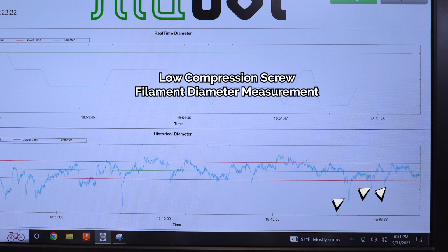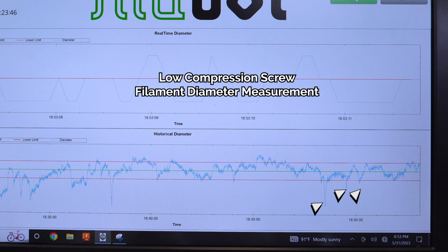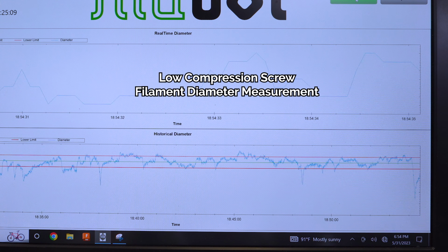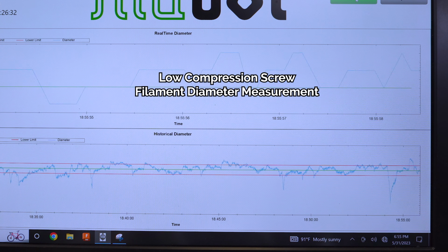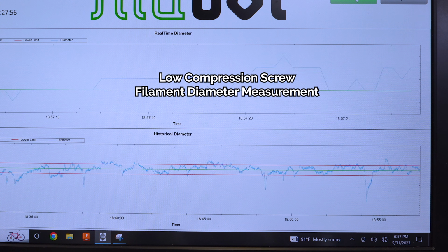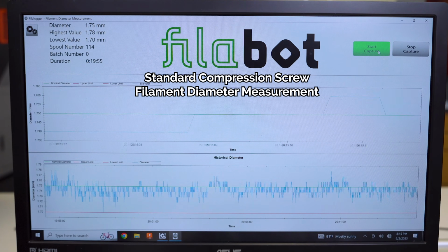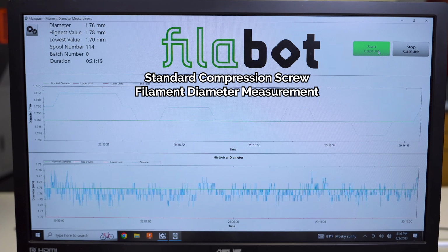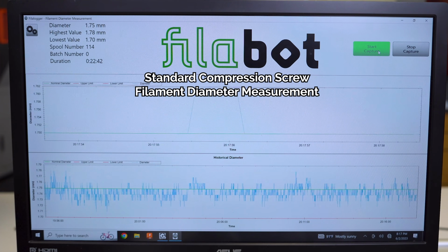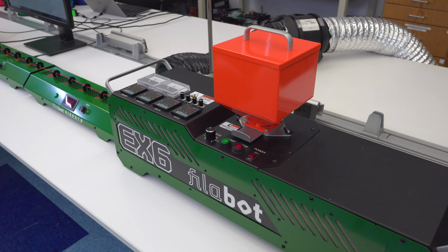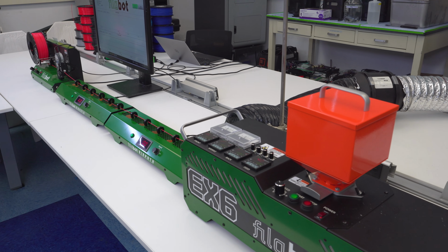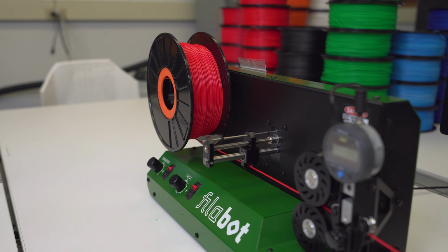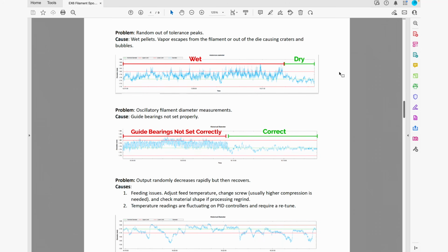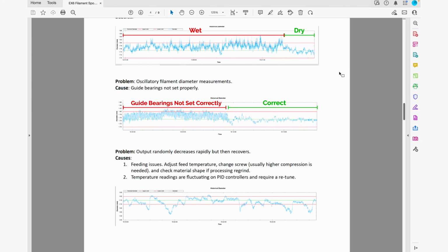These steep, random drops indicate that there is a feeding issue, almost as if there are gaps in the flow of material causing the filament diameter to decrease rapidly. Now, there are other issues that could cause this, but it's likely that I need a higher compression screw. I switched to one with a standard compression and no longer saw this problem. Of course, I could have skipped this troubleshooting, but I wanted to give an example of how I used the filament diameter measurements to change the configuration of the extruder. I have several more examples on that previously mentioned document, which you can check out.